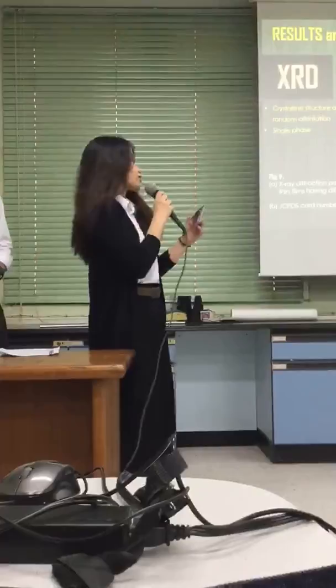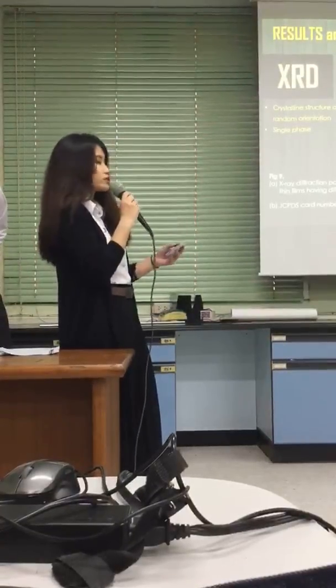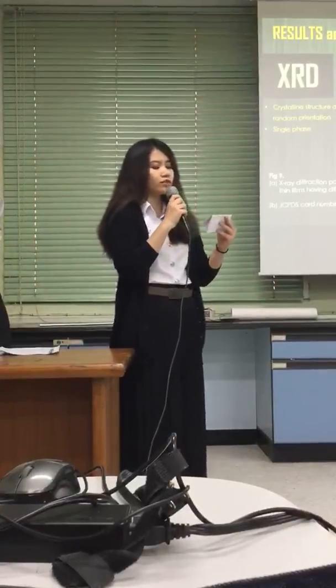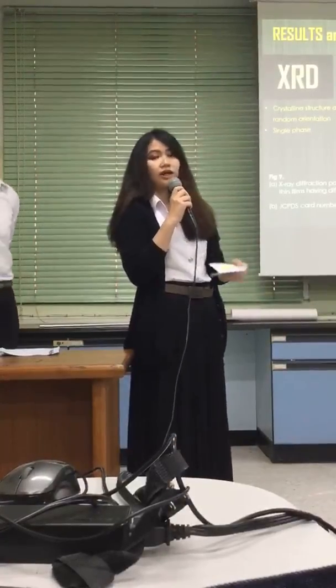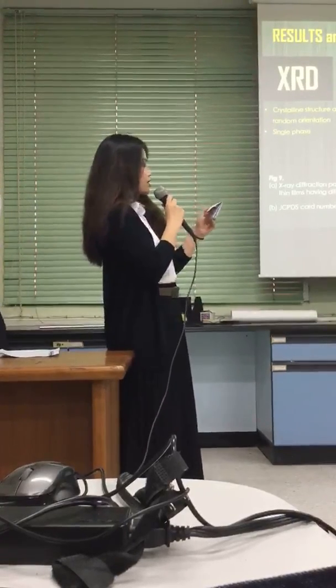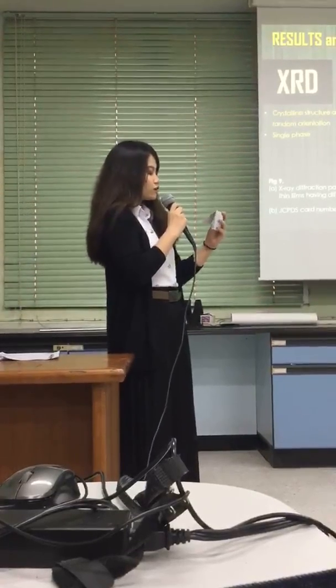Results and discussion. Figure 9 shows the X-ray diffraction pattern of samples having different titanium concentration. The pattern shows that all samples are in good agreement with Joint Committee on Powder Diffraction Standards, card number 89-1397. All samples are single phase and no evidence of secondary peak from titanium substitution.